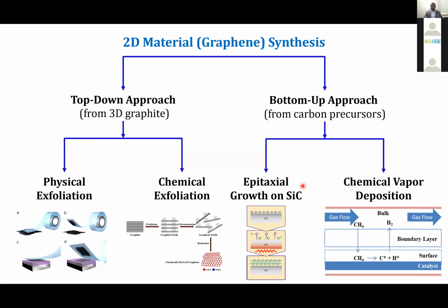In the case of epitaxial growth on silicon carbide, an insulating substrate, if you heat it, we try to boil the silicon carbide so that the silicon atoms evaporate, and then you have only carbon atoms on top, which can hybridize to form layers of graphene. It's a very time and energy consuming process, because in order to evaporate silicon you need to heat it at a very high temperature of 1400 degrees Celsius, as well as very high vacuum. So it's a very expensive process. However, you'll be able to get high quality graphene.